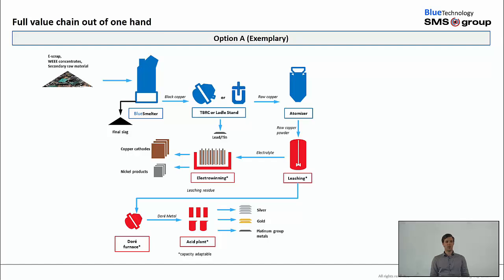So how does the process look? Starting from the Blue Smelter, where we add the scrap and produce a black copper, as mentioned before, we collect all the metals that come within the scrap into a liquid phase. This can then be transferred to a further process or sold to the market as a solid black copper product. If you decide to process it further, you transfer the material to a TBRC or ladle stand. In this TBRC or ladle stand, you oxidize the material and produce a lead-tin alloy or slag, and then transfer the raw copper into further processing steps.